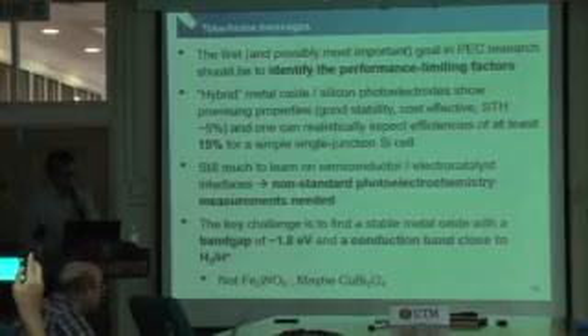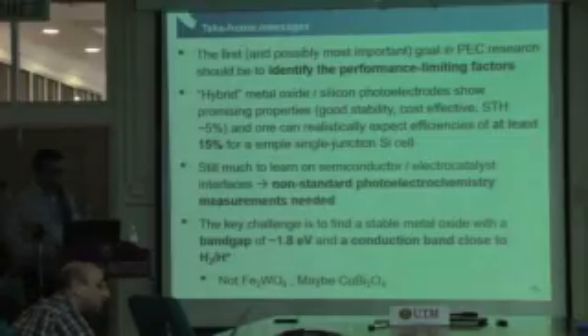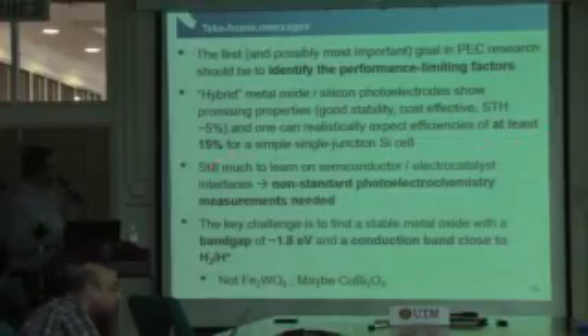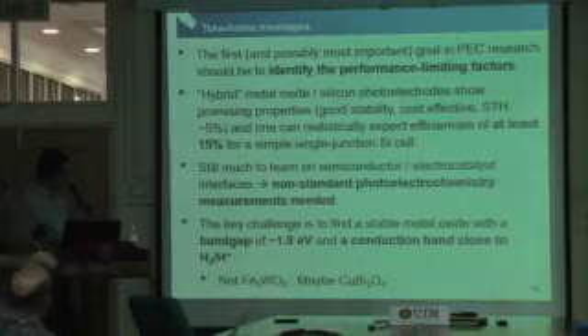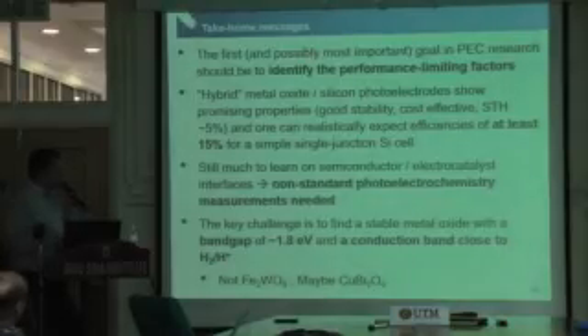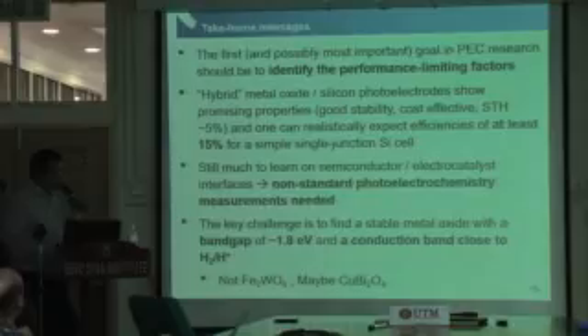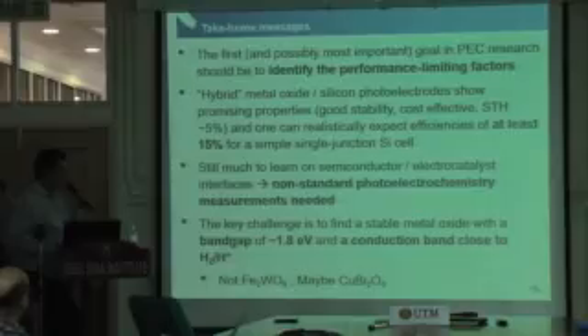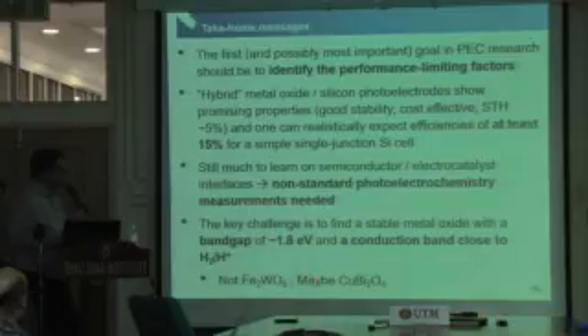Second, for the combination of hybrid metal oxide and silicon photoelectrodes, we expect to get at least 15%. And there's still much to learn on the semiconductor catalyst interfaces. For this, we need to do non-standard photoelectrochemical measurements. The key challenge, as I've said before, is to find a stable metal oxide with a 1.8 electron volt band gap and a conduction band that is close, or not too far, from the hydrogen evolution potential. We showed that it's not iron tungstate, so don't work on this, but it may be copper bismuth oxide.